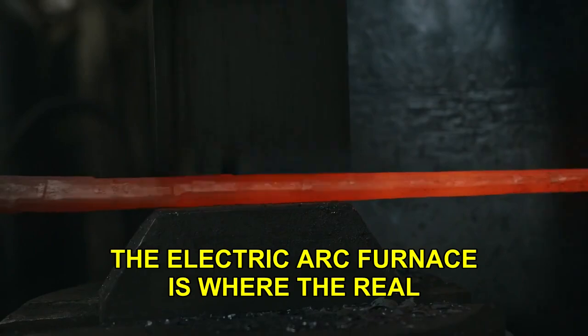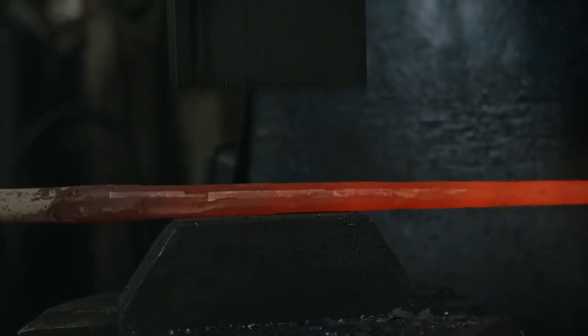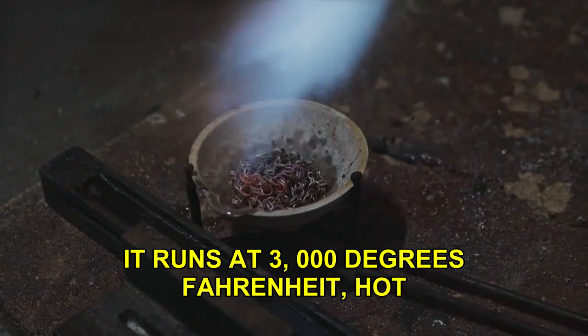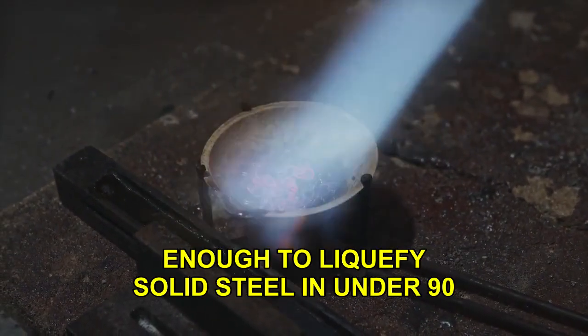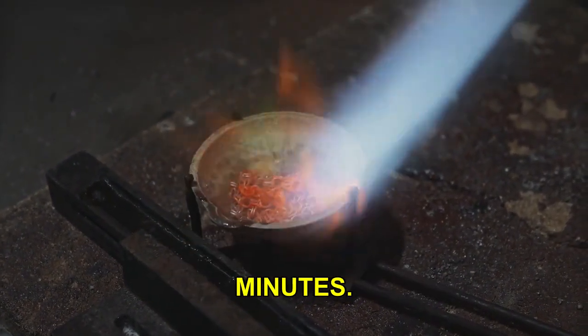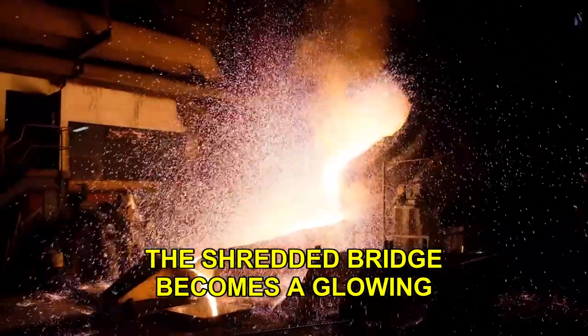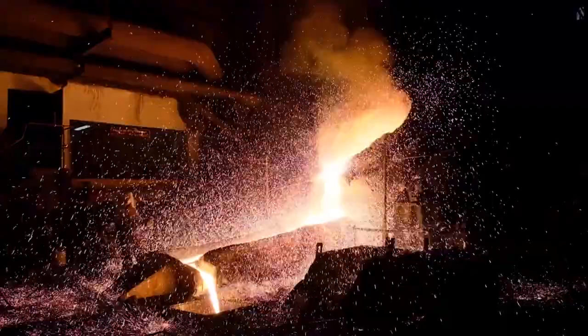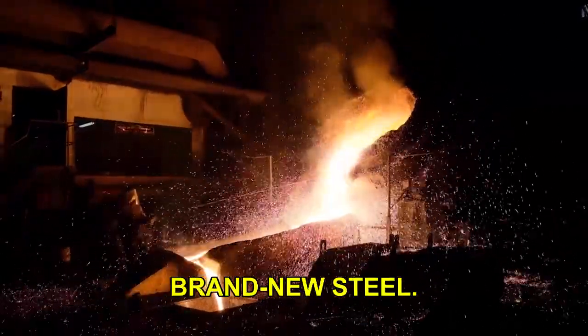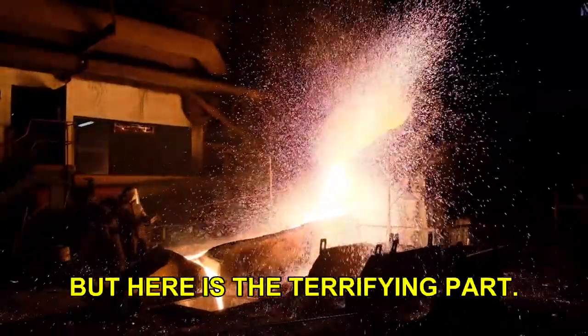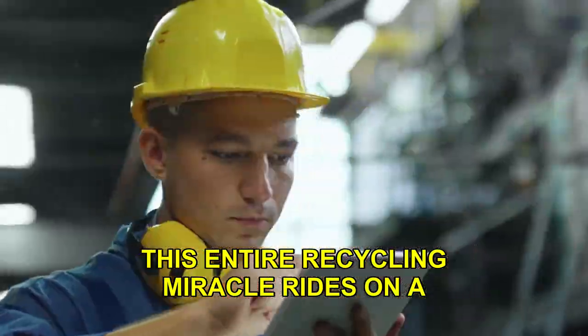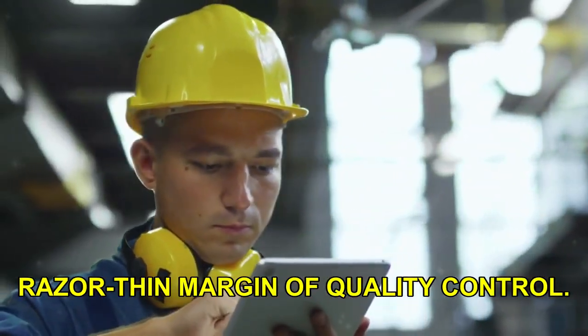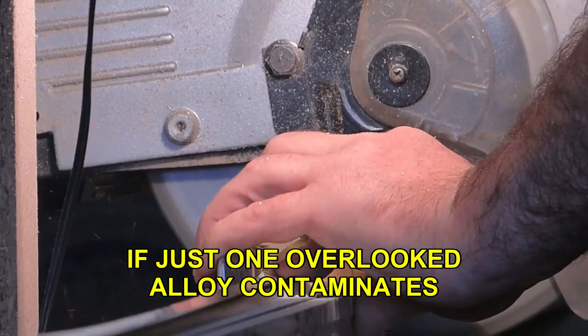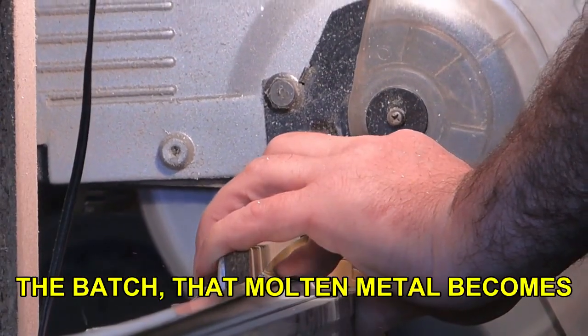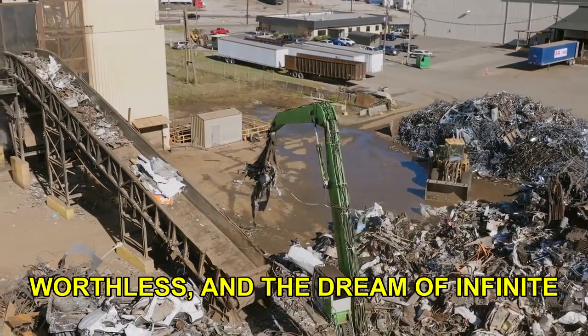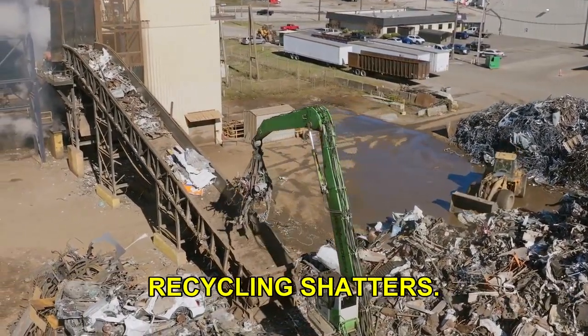And that furnace, the electric arc furnace, is where the real transformation happens. It runs at 3,000 degrees Fahrenheit, hot enough to liquefy solid steel in under 90 minutes. The shredded bridge becomes a glowing orange river, and for the first time in its existence, it's indistinguishable from brand new steel. But here is the terrifying part. This entire recycling miracle rides on a razor-thin margin of quality control. If just one overlooked alloy contaminates the batch, that molten metal becomes worthless, and the dream of infinite recycling shatters.